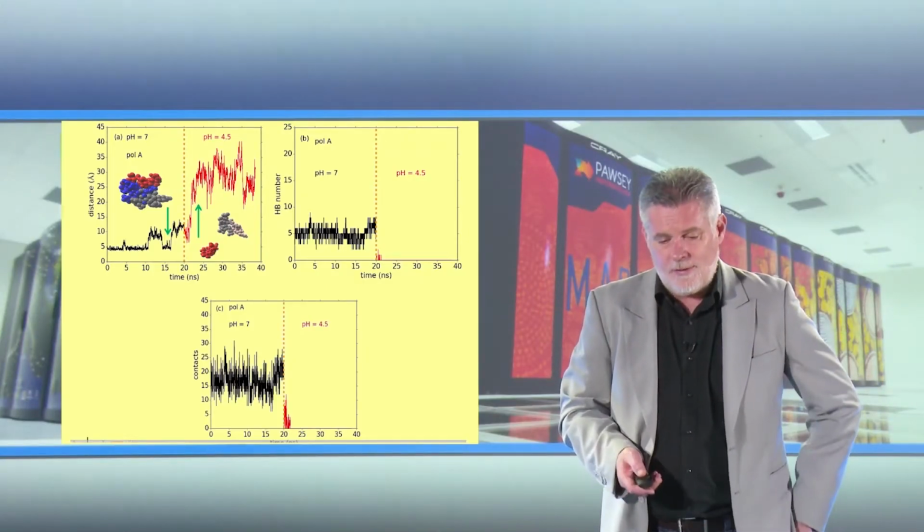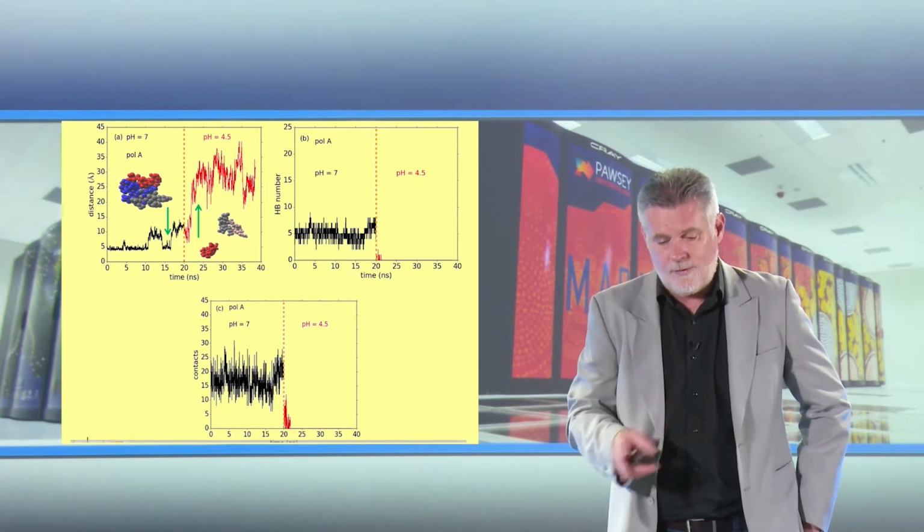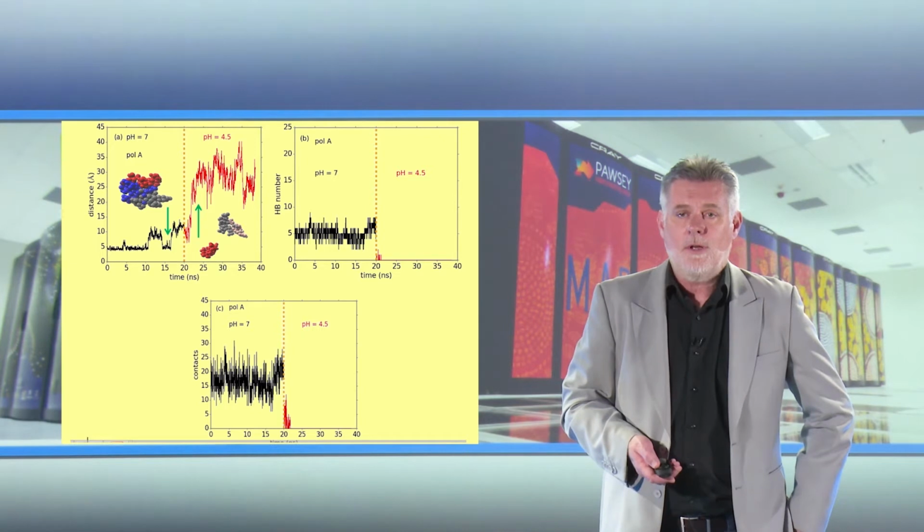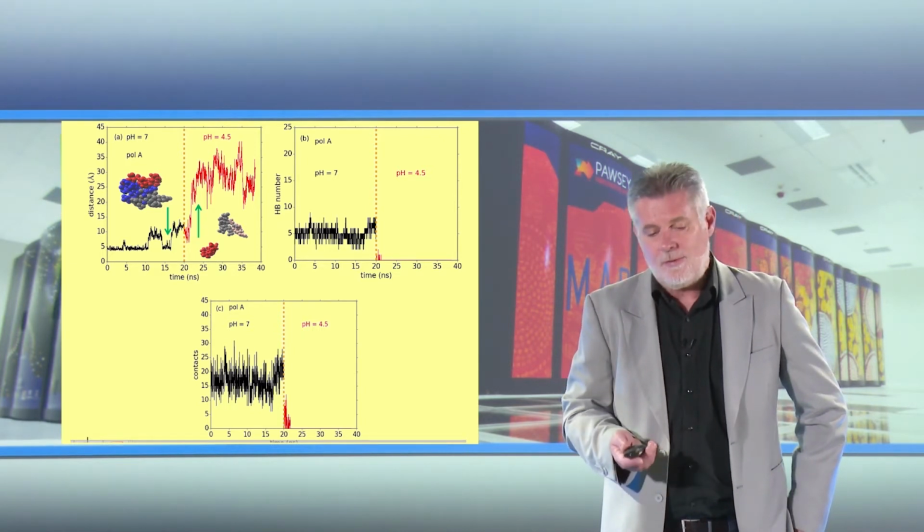So interesting possibilities. We ran simulations there and you see some profiles here which show that indeed, as you simulate that in time, once you switch the pH, and in the top left-hand corner that happens around 20 nanoseconds, these are short systems and preliminary simulations we did, but it really blows apart. Once that carrier polymer turns positive, it blows away from the lysozyme, from the positively charged drug, and looks very promising. Okay? So going on a little further, we can probe further with quantum chemistry and understand more about whether these things could work or not.